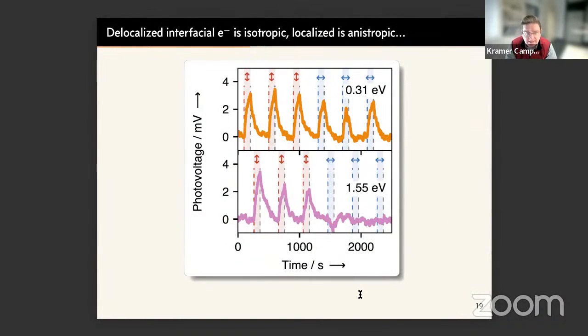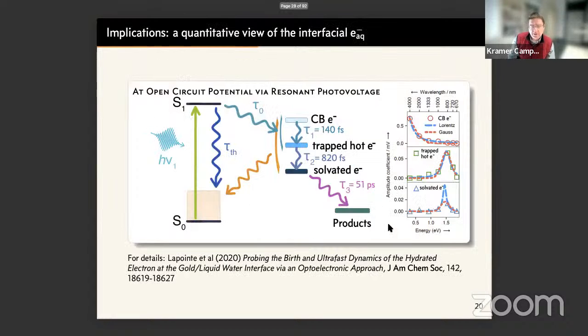Another interesting aspect of this data is that it shows a clear polarization dependence. If you probe at short times, at low photon energies, at long wavelengths, there is no polarization dependence, so you can change the polarization of this second pulse. If you probe at the higher photon energy, so this localized state, you see a clear polarization dependence. Somehow the symmetry of this resonance is changing in time. If you're interested, we can talk about this in detail, or you can look at the paper that came out last year, where you can quantify all of these details.